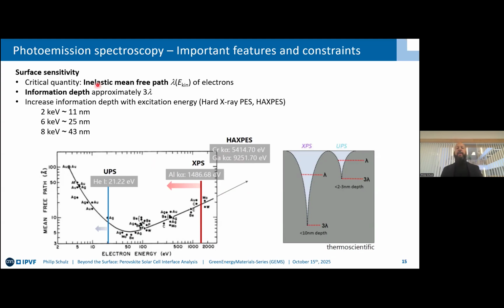The information depth you can approximate with about 3 lambda. You always need to consider this type of profile that you see here. So of course, you're always getting most of the signal from the surface, but you also get signal from deeper down in the subsurface region. I noted down just for general sense of orientation, some values of what you can expect for information depth for different photon energies when looking at the first core levels in the first several hundred eV binding energy range.